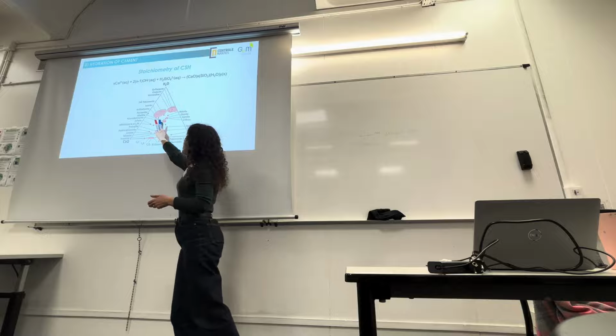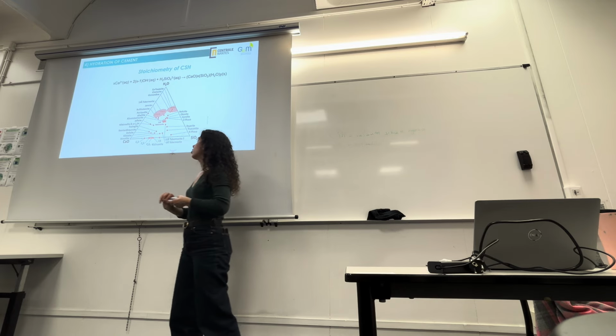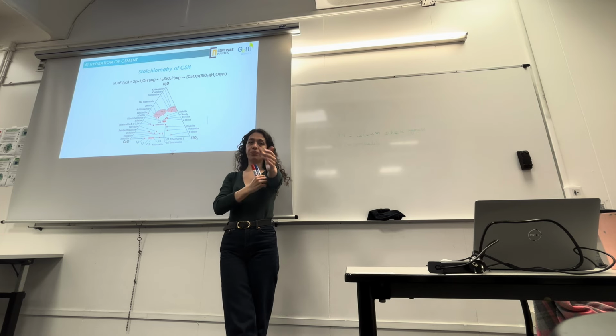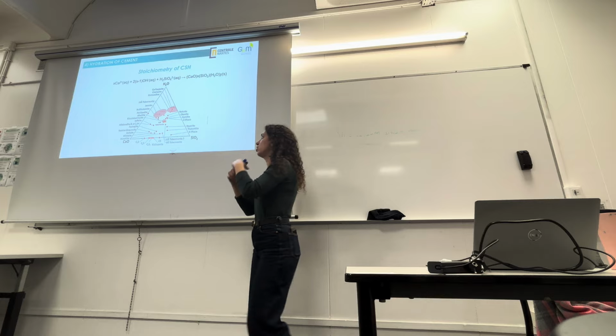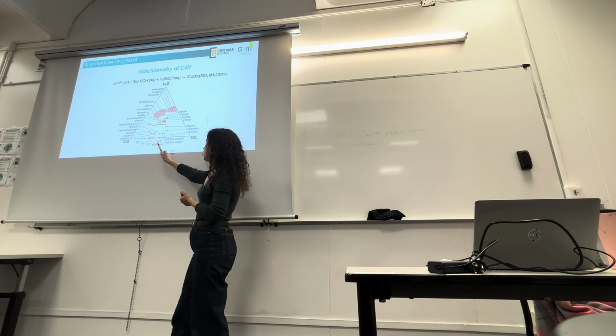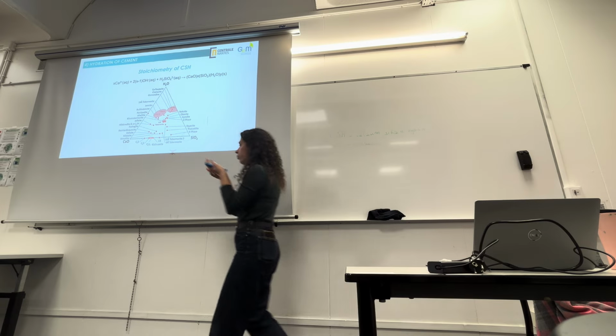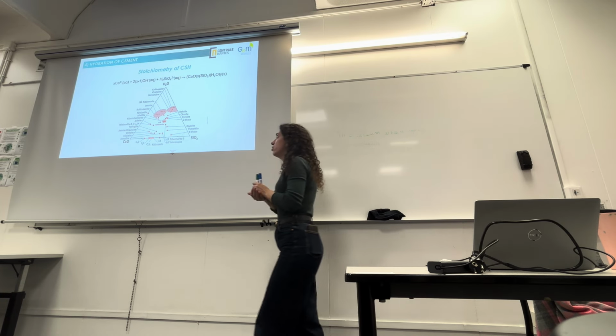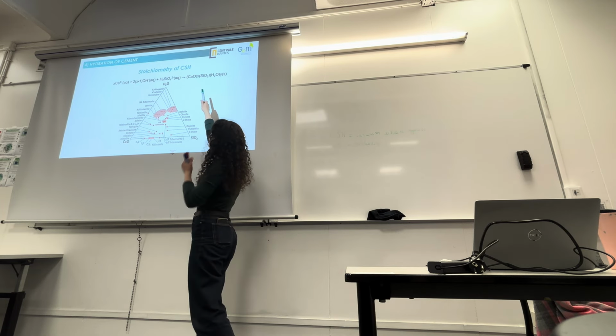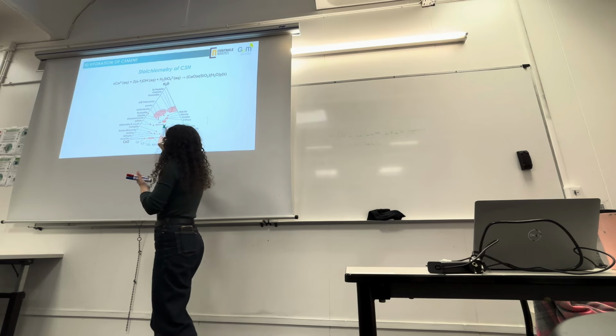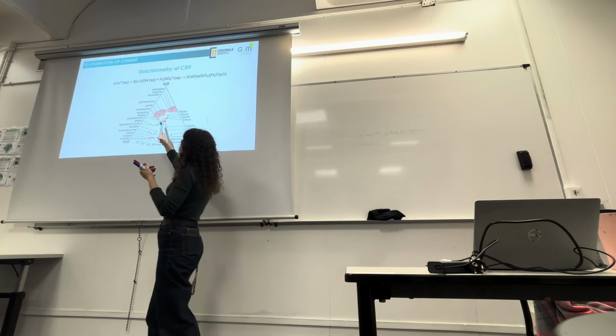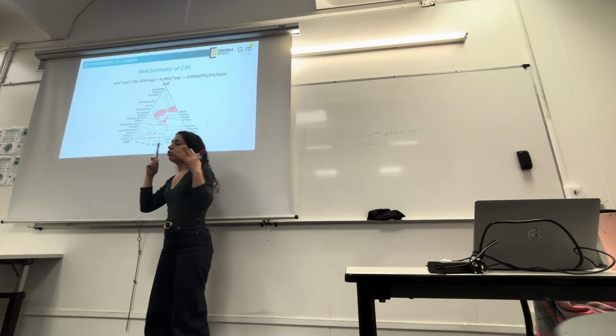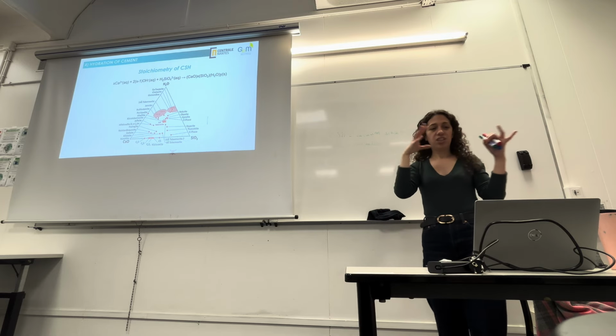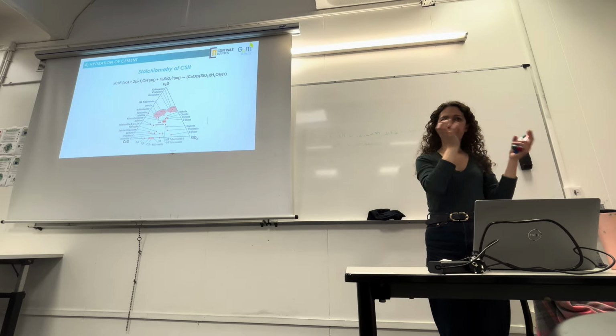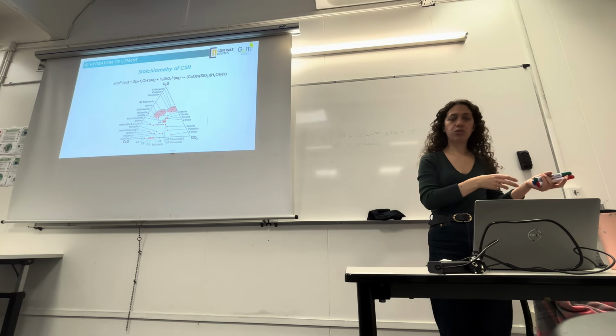And so the A with the circle, the Swedish A, angstrom, is the distance between the layers of the CSH. So here we have 11 angstrom, and here you have 10 angstrom, 9 angstrom. But we know by research that the CSH from cement, even though we don't have its specific stoichiometry, is quite close to tobermorite. But some other researchers say it's closer to jennite stoichiometry. But you don't have to remember that. Just know that CSH exists in various forms. They exist as natural minerals. They exist in cement, but in cement we don't know the specific geometry of this CSH.